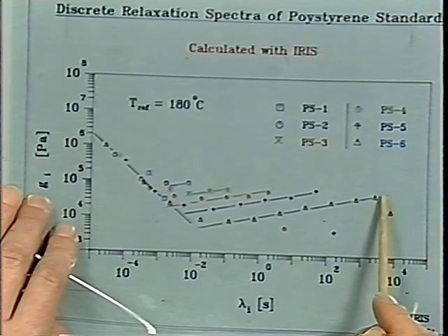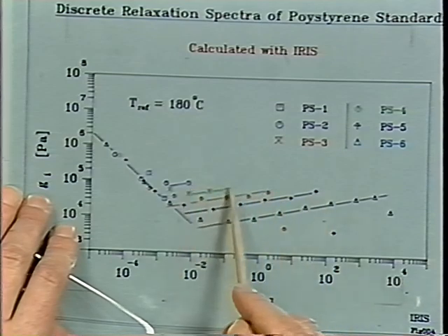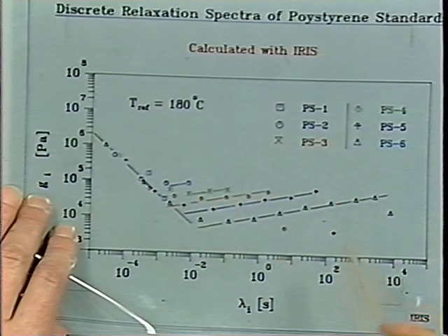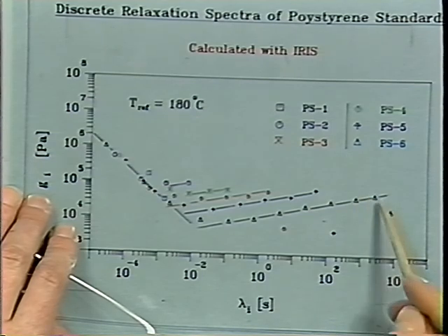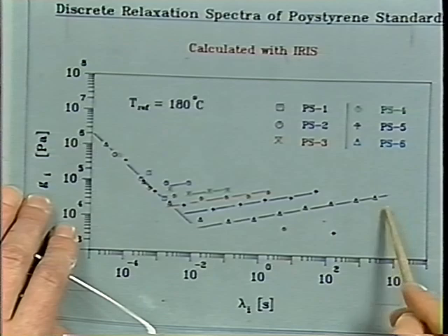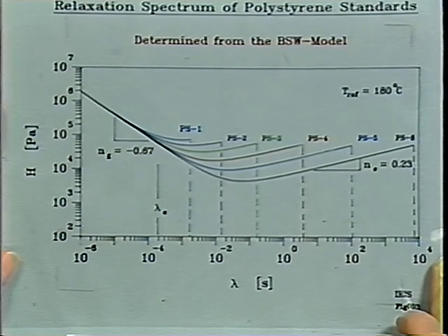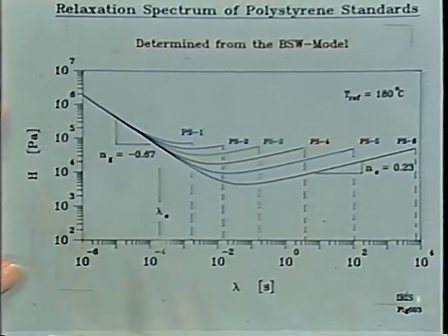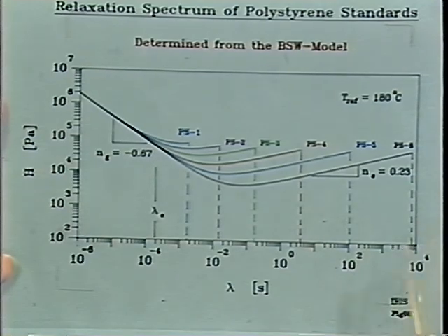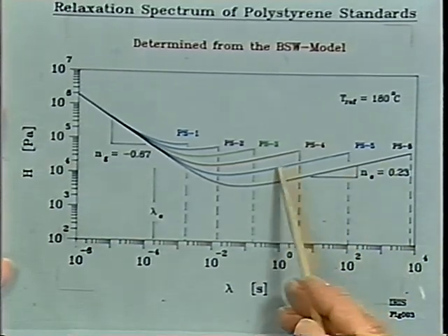One other thing to note is that the top of those is always at the same position of those points. And then the cutoff is somewhat gradual, but the gradual transition here is an artifact of our discrete representation of the relaxation spectrum. So if we go now to a spectrum which is continuous, then the cutoff will be sudden, will be abrupt, but we maintain the slope of the curves. Here, let me move it in here. We're plotting H as a function of the relaxation time.